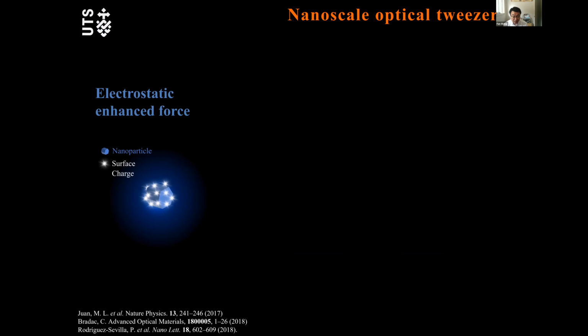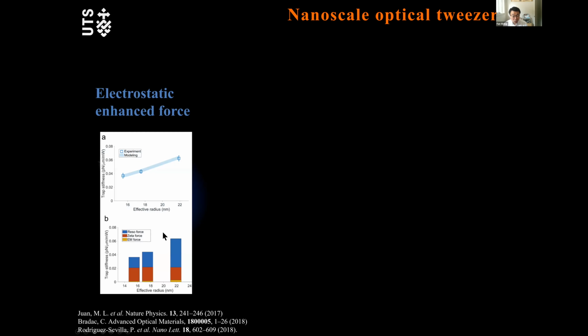Currently, there are several hypotheses for the reason. One is electrostatic enhancement, which is about the surface potential: if you have lots of surface charge, it will increase the polarizability. Daniel mentioned this, but it doesn't work here because we did some experiments. If we use particles with the same zeta potential, the trap stiffness is still different. And from Daniel's theory, if you have the same zeta potential and even different sizes, your trapping force should be the same.